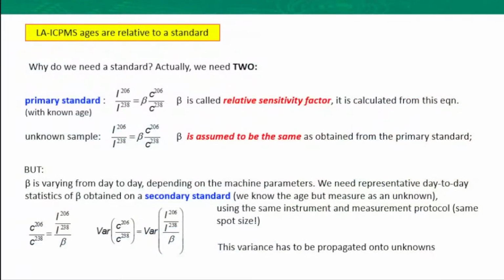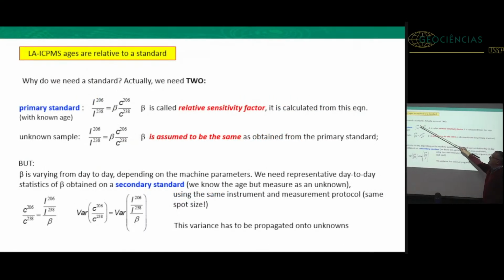The second important point is the standards. Laser ablation ICP-MS ages are relative to a standard. So why do we need a standard? Actually, we need 2 standards. So we have a primary standard because what we measure on our fantastic mass spec is nothing else than an intensity ratio, 206/238. And any mass spec is doing wrong. You know, a mass spectrometer is always measuring something which is wrong. It has a mass spectrometer fractionation effect,